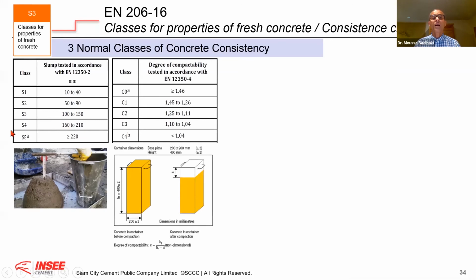Now, other countries, they have a degree of compactability. For example, in Switzerland, they also use the slump test, but they use also this degree of compactability. It's very simple. You have a box, you fill it without compaction, you fill the box with concrete. After that, you vibrate the concrete with a certain vibration frequency and certain time. Okay, and you measure the slump. And the degree of compactability is the ratio between H1, the height, divided by H1 minus the slump. That is the degree of compactability. The lower the value, the higher is the slump of the concrete.